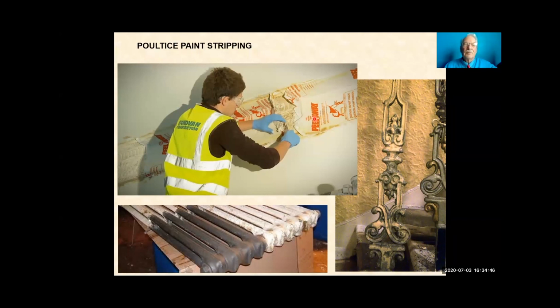You leave it for the appropriate time, and then you peel it off, and it brings off the paint with the coat, with the paper. Very effective. You might have to do it more than once. And again, you might have to do some detailing at the end to just clean up the areas where the poultice hasn't got very well. But I recommend that as a good way of getting rid of paint.